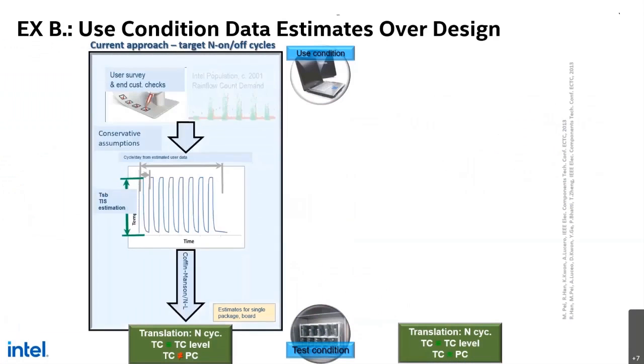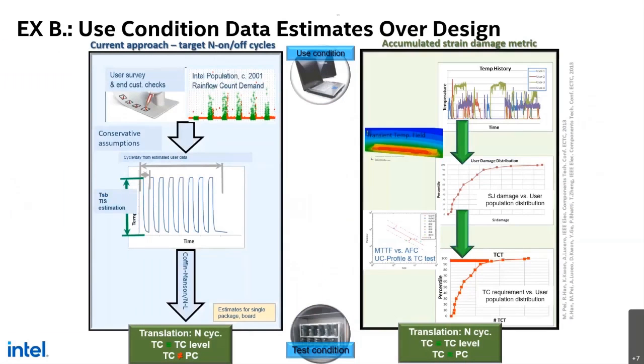Previously we would have done just a number of cycles, and we would come out to some kind of a test requirement that doesn't mimic what happens in the real use in the power cycle case. But if you want to do telemetry and actually measure the temperature profiles on the right-hand side, you can compute transient temperature fields. You can then compute solder joint damage. You can have a master curve that shows you by geometry what to expect, and then you can come up with a requirement.